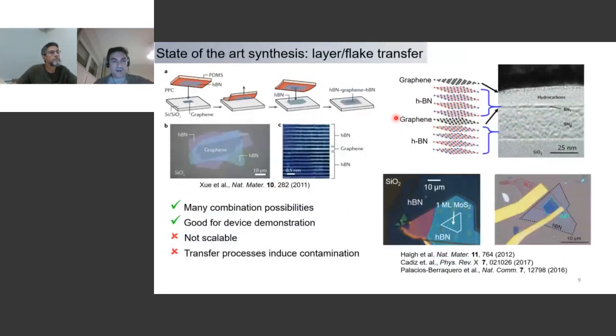So, what is the state of the art in terms of synthesis? As I mentioned already, most of the time people will take flakes from a bulk crystal and transfer them to a substrate, and they do sequential transfers so that they can build up their structures. It can also be layer transfer, meaning you grow HBN or graphene by a technique like chemical vapor deposition over a large area, and then you remove this layer from the host substrate and start piling up different 2D materials.